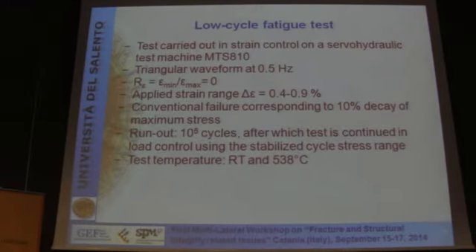We considered a conventional failure when the maximum stress reached a decay of 10% of the load. And finally, we considered a maximum number of cycles of 10^5. After this, the test is continued in load control. At the moment, I will present only two temperatures, room temperature and 538 degrees.